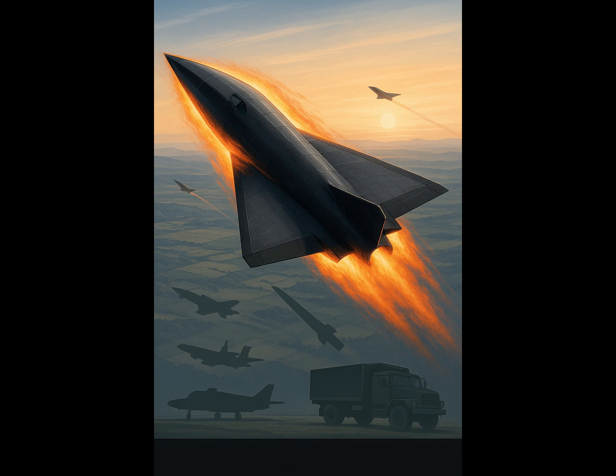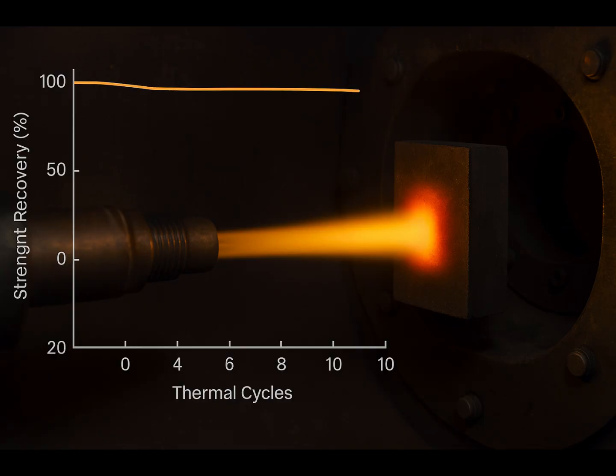Objective: fabricate and arc jet test a prototype thermal protection heat shield tile, then verify survivability across multiple high-temperature thermal shock cycles without catastrophic failure, that is, no spallation, delamination, or through-thickness cracking, confirmed via post-test NDE, and retain mechanical properties.